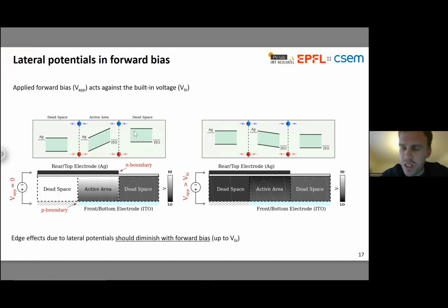Yeah, a very specific prediction of this lateral migration hypothesis is the voltage dependence, because we see that as we apply forward bias, we start to nullify these lateral potential differences. And eventually, once we cross the threshold of the built-in voltage, the potential differences actually reverse in direction. So we do expect, on the basis of this hypothesis, at least for the particular device architecture that we're working with, we should see a diminishing of effects with forward bias up to the built-in voltage, and then maybe a reversal afterwards. So I wanted to test that prediction.